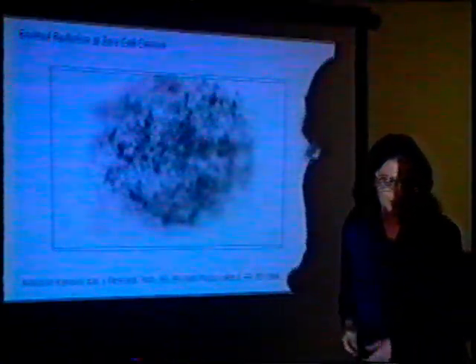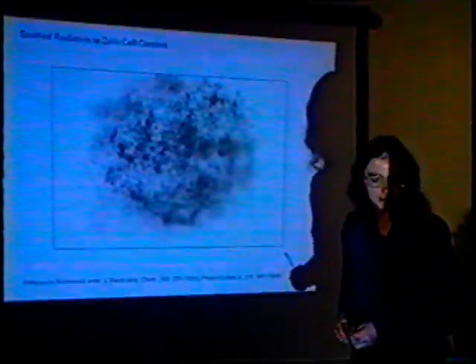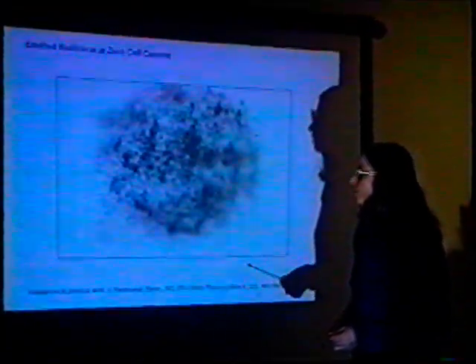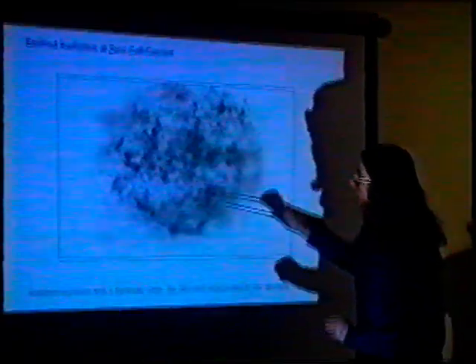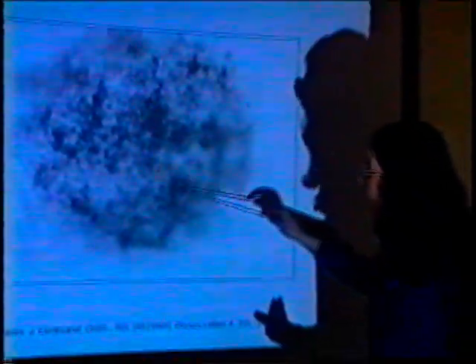After we have conducted these experiments, we have taken the crystal and put it into a light-tight envelope. We've put a very thin membrane over the crystal and taped it in place. And then on top of that, we've put photographic film. And we've allowed it to be exposed to the photographic film for 3 to 5 days. And afterwards, we have the film developed. And you can see here that we're getting radiation of some sort being emitted from the dark spots here. You can see the outline of the piezoelectric crystal, and you see these distinct spots occurring.